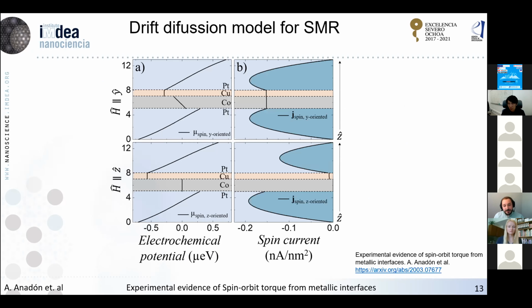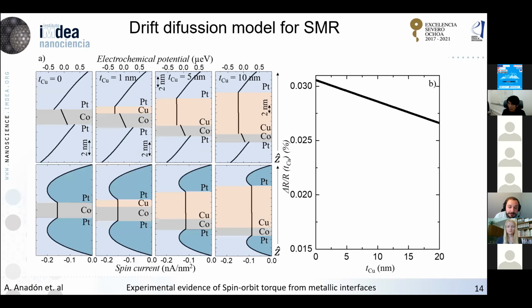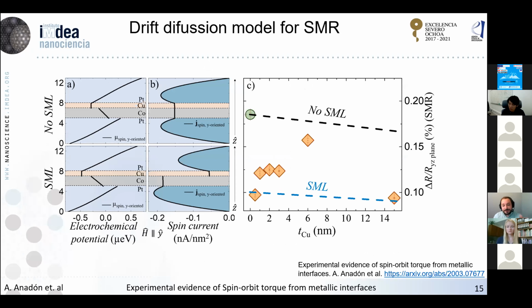As I said, there are many things going on at the same time, but we think that basically by our interpretation from the diffusion model, we see that this decrease of the spin Hall magneto resistance mimics very well the result for our model. So we think that this decrease of the spin Hall magneto resistance most likely comes from a spin memory loss. But as I said, this is not the whole picture, because to have the whole picture, you need to put all the phenomena together, and it is very challenging to do this in theory.